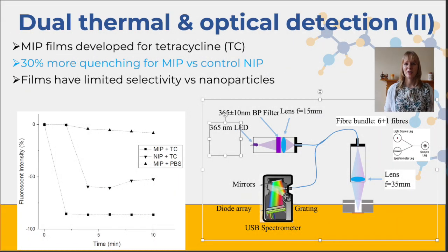We worked with a system for tetracycline, which is another antibiotic. Again, a film was developed, a film using 9-vinyl anthracene, and what we did is we exposed that film to concentrations of tetracycline. As soon as we did that, we could see that there was a drop in the fluorescence. So essentially you saw a quenching, which is because you have binding, and that has an impact on the interaction that the fluorophore can get.